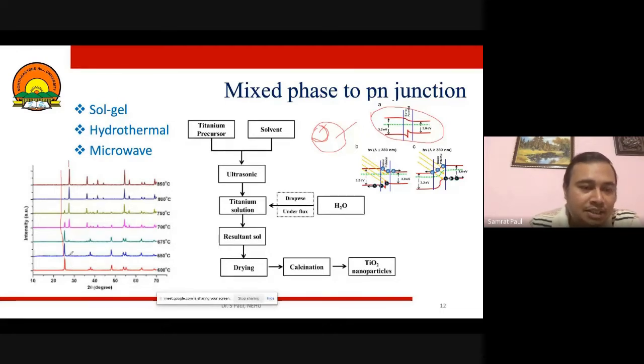So while changing the temperature during the synthesis, at 850 we get pure rutile, and at 600 we get pure anatase. And at intermediate temperatures we can control the amount of rutile and anatase, thus making each nanoparticle have both rutile and anatase phases in it, and they will behave like a PN junction diode. And when we operate them, the current or the electron will flow unidirectionally, and these can be used in various ways to design a photocatalytic reactor as well as a photovoltaic device like a solar cell.